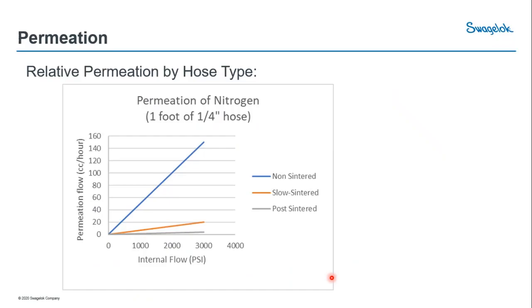What we're looking at here is slow sintered, and then you've got post sintered. You'll see the orange line right here. Again, these two have much lower permeation rates. Slow sintered means that as the core tube is extruded, they're adding heat to the process so that the elements of the Teflon or PFA will bond tightly together. And then post-sintered is your least amount of permeation through the hose.